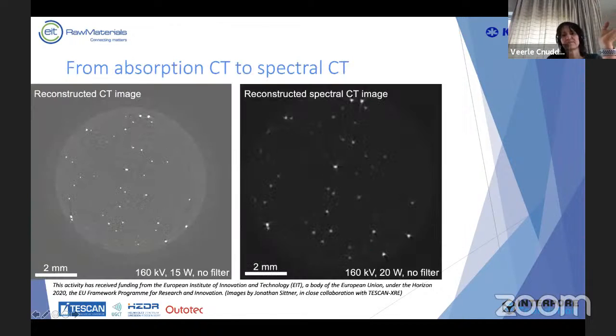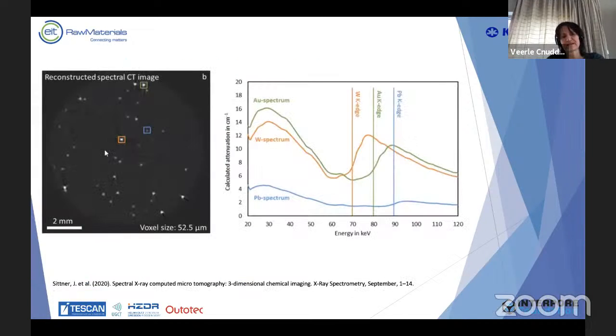If you use a spectral detector, this is the image that you get, and you see that the image quality is coarser. This is because the resolution of the detector is lower, fewer pixels, but you get a spectrum. This means that you can then identify, okay, in this grain, how does the spectrum look like? It allows you to say, okay, this is tungsten, this is gold, and this is lead. So you can distinguish the difference based on the spectrum that comes out.